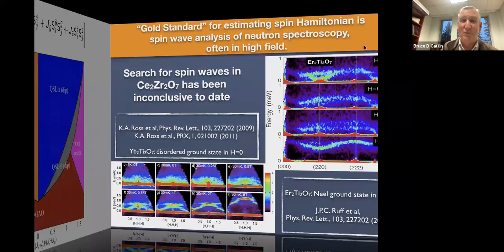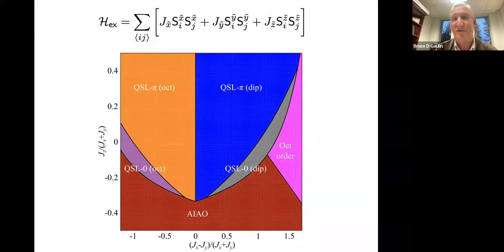And so instead, what we do is we get together with our theory friends and we try to analyze the data that we do have. This is the underlying microscopic Hamiltonian that's expected for these dipole-octupole spin 1/2 degrees of freedom decorating a pyrochlore lattice. You've got these X, Y, and Z components of the spin 1/2 degree of freedom. It's the Y component which is associated with the octupoles, at least that's the conventional way of describing it.